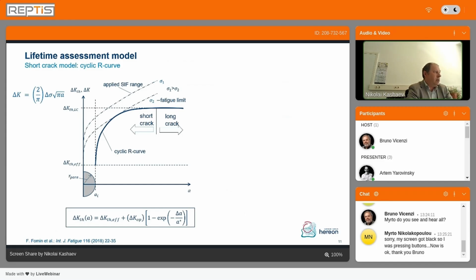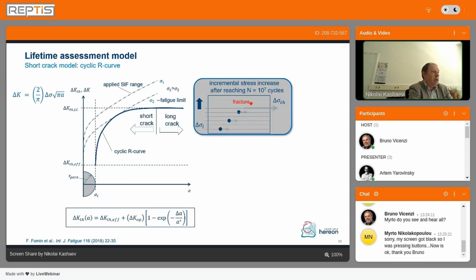Delta K is equal to 2 divided by pi, delta sigma, and square root of pi a. It's our stress intensity factor. And the condition whether the crack will propagate or not is exactly there if the so-called crack driving force, our delta K, has a tangential condition to this cyclic R-curve. The question is how we can identify our cyclic R-curve.